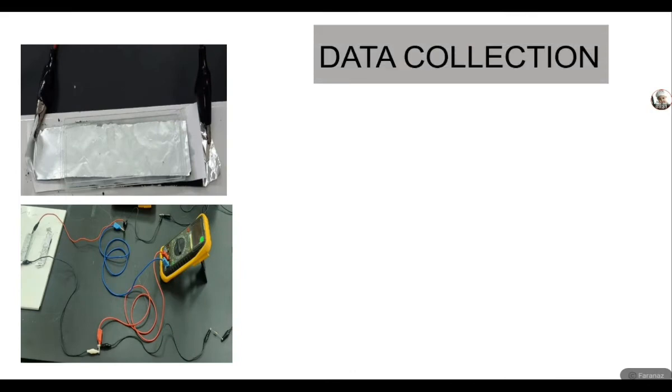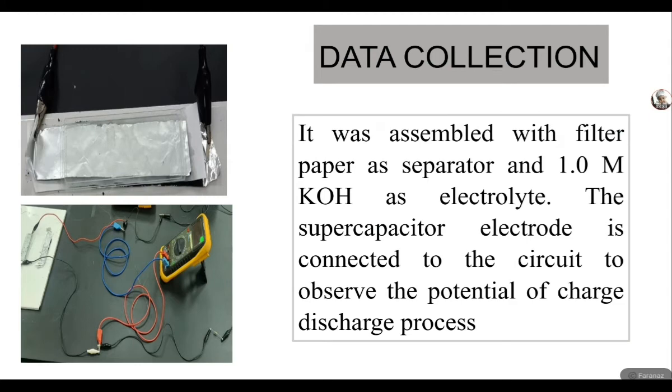Data collection. It was assembled with filter paper as separator and 1 molar potassium hydroxide as electrolyte. The supercapacitor electrode is connected to the circuit to observe the potential of the charge-discharge process.